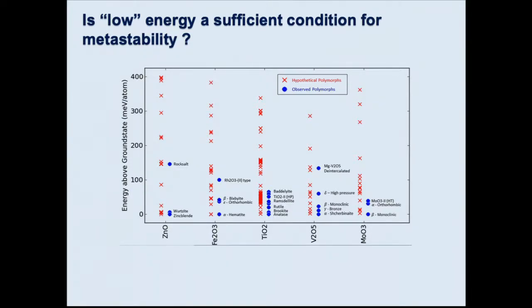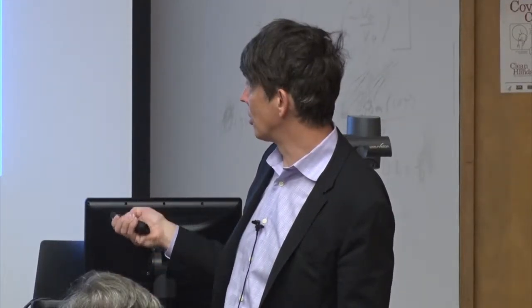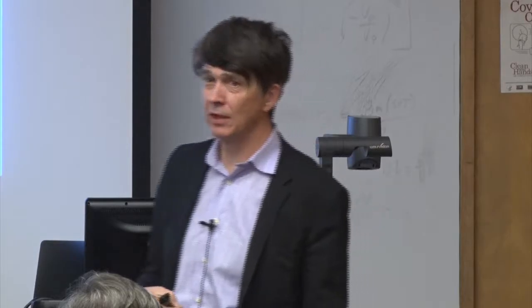So the known metastable compounds are in that range, but it turns out there's a ton of other ones in that range. So mathematically, what we have here is a required criterion, but not a sufficient criterion. Yes, metastable crystalline compounds have a fairly low energy range, but there's a ton of other ones that are in that range and nobody ever sees them. And maybe you think that somebody should try harder to see all these weird polymorphs of TiO2, but I don't think so. There are like 20,000 papers on TiO2, order of magnitude. I would be shocked that they would have never observed any of these.